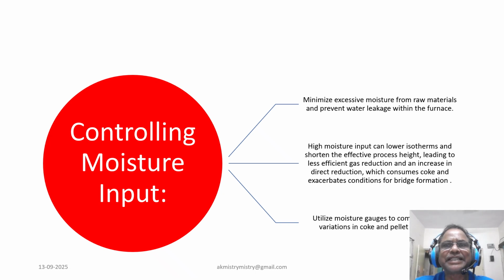So we can say that high moisture input also lowers the isotherm and shortens the effective process height, leading to less efficient gas reduction and an increase in direct reduction. And once direct reduction increases, the consumption of coke also increases, leading to a higher coke rate in a big way, and there is a reduction in production and productivity. To counteract these, utilizing moisture gauges to compensate, we have already mentioned that their calibration and monitoring is to be done at regular intervals of time.